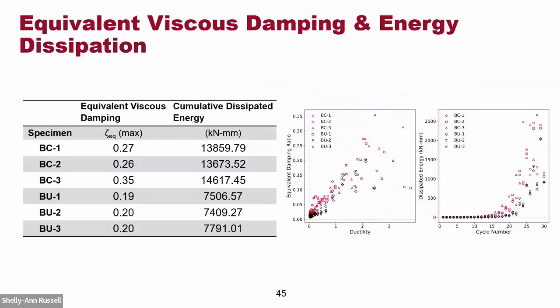We also calculated the equivalent viscous damping, by taking the maximum hysteresis loop energy and dividing by the triangular area of that hysteresis loop. We got the equivalent viscous damping of C sections more than U section. And you can also see the energy dissipation of these specimens in this graph.